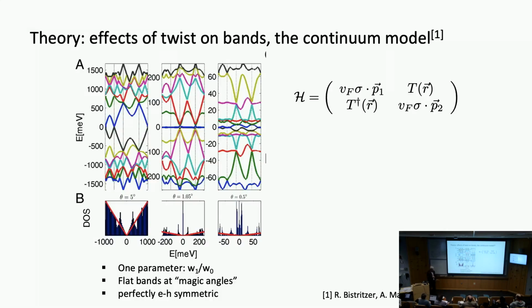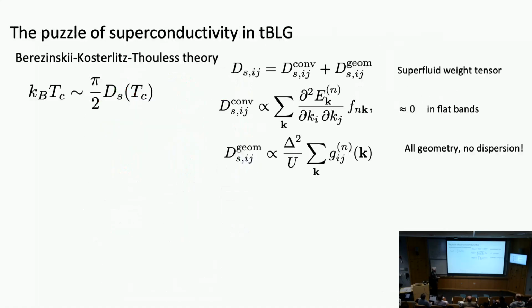They're still not quite realistic enough because they miss certain important features. For example, there is no band gap between the flat bands and the rest of the bands. And this is something that I emphasize here because the presence of band gaps separating the flat bands from the rest is a crucial feature of the system. Without this, you wouldn't be able to find any of the complicated phenomena that I was alluding to, and I'll describe in more detail shortly.